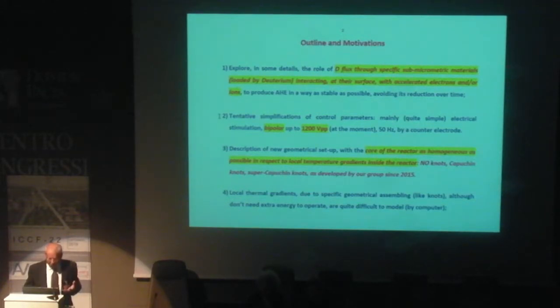The point is, before we began just using electrons, but it was not enough, and we added ions. To move ions to get flux, you need quite a large voltage. In this experiment, we work up to a counter electrode of 1,200 volts, sinusoidal.